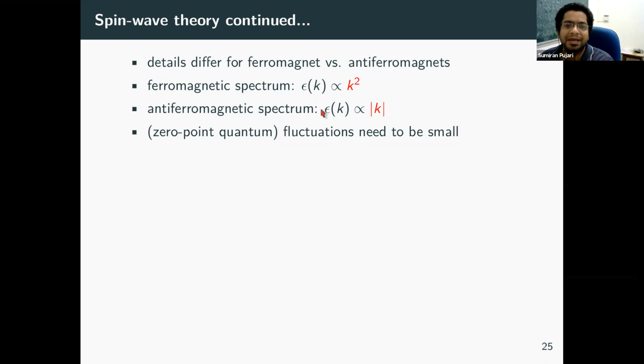By spectrum, I mean that in your lattice you have a spin wave, and given that spin wave, the quantized excitation corresponding to that wave vector, what is its energy? So the energy of ferromagnetic spin waves behaves as k square, whereas for antiferromagnetic spin waves, it's mod k. This is a very key difference, because it controls the strength of quantum fluctuations, and one has to go back and calculate the zero-point fluctuations due to these quantized spin waves. The fluctuations are indeed small, and it turns out you can show them to be small only in 3D, and in lower dimensions it's not the case.